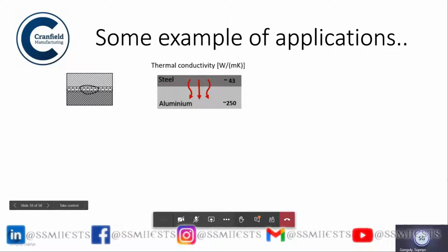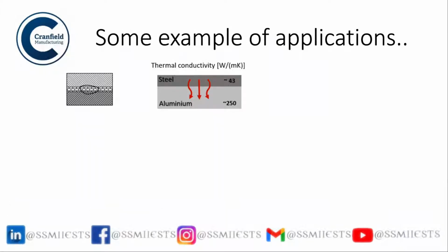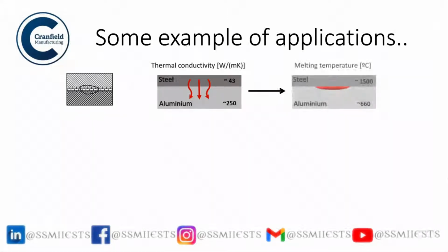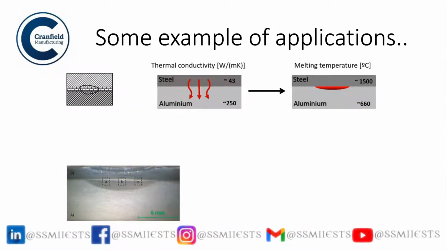So some applications now. As I said, you can have a scenario where you conduct the heat from steel to aluminium, because the conductivity of aluminium is much higher as compared to steel. And you can always use a copper backing bar here. So the heat is conducted from steel to aluminium, and you principally avoid melting, the creation of a fusion zone with all molten steel and molten aluminium, because that will be catastrophic in terms of intermetallic formation. And you can see nicely the difference in the melting points of both of them, and that gives you the basic possibility to create such a joint.